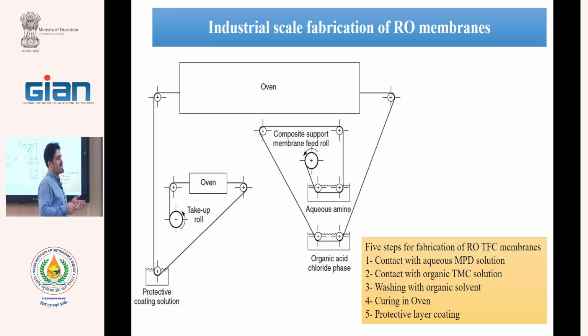For reducing the defect possibility, we coat a third layer for protecting the RO membranes. Therefore, the fabricated RO membranes go to the protecting coating solution. Usually it is polyvinyl alcohol, PVA solution with low concentration, and only a layer coats the polyamide layer, and it goes to the second oven for drying. This PVA layer, during the application of the membranes, within 1 or 2 days, will be dissolved in water and will be removed from the membrane surface. Okay? Therefore, this protective layer is not stable and will be removed rapidly. This reduces the defect possibility of the membranes.